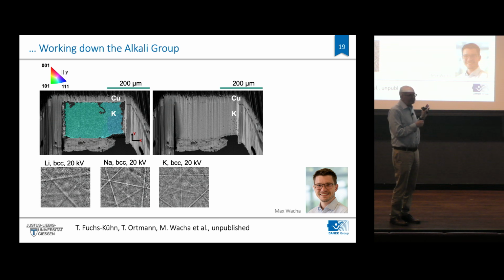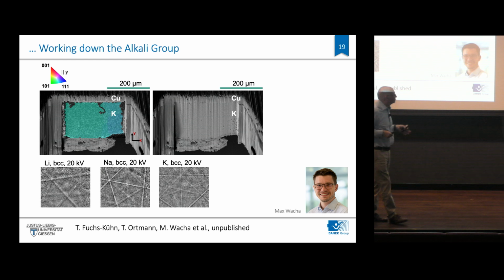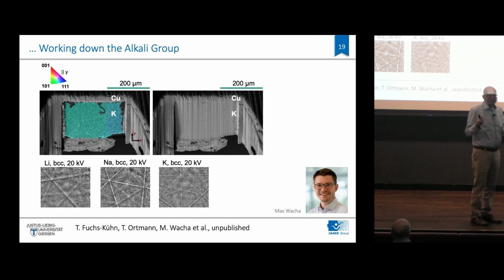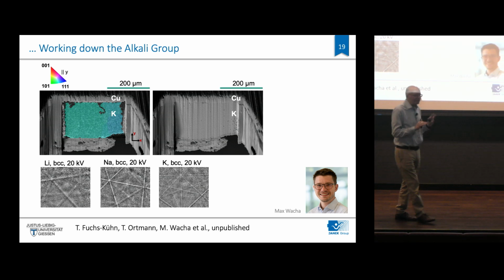But it seems that particularly if you use interlayers, that helps more preferential orientation. But I think it is too early to conclude on that. Of course, this is an interesting and very important question. What we also see in the EBSD analysis is that we can analyze the deviation from the perfect orientation, and we see that the orientations also show some ripening with time. There are lots of details I excluded right now.